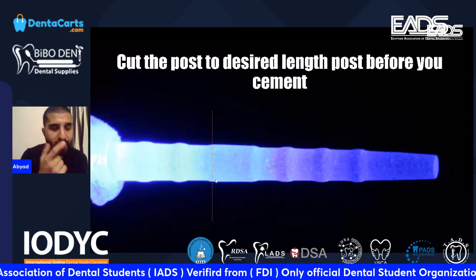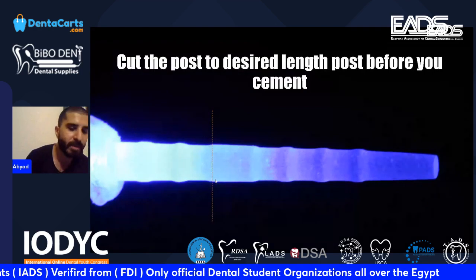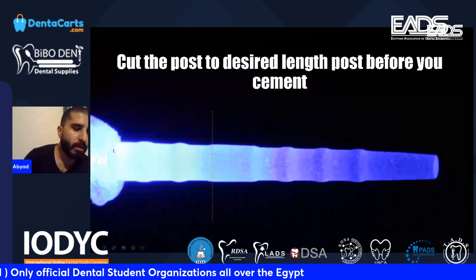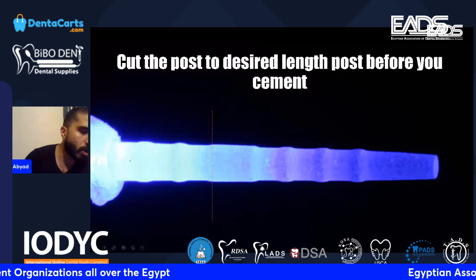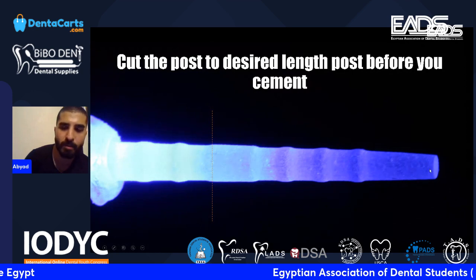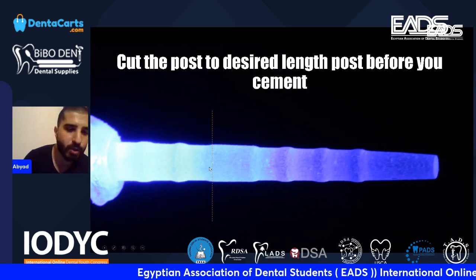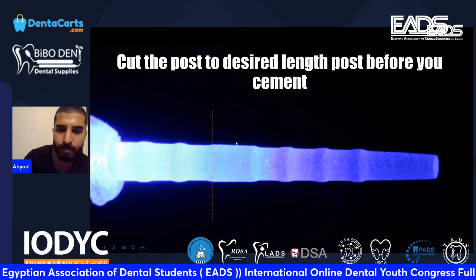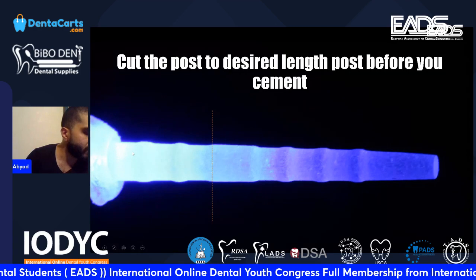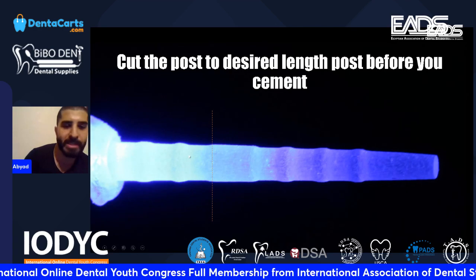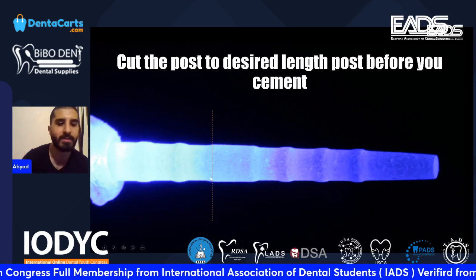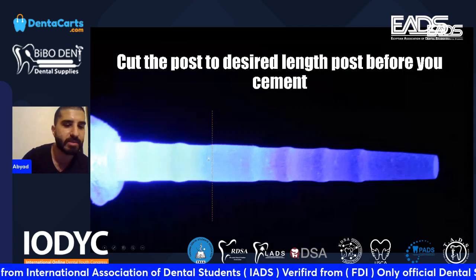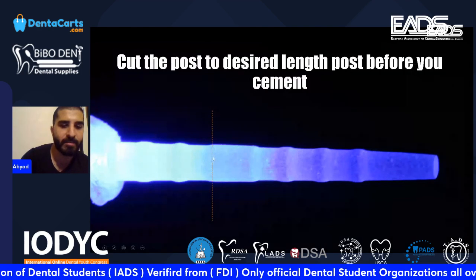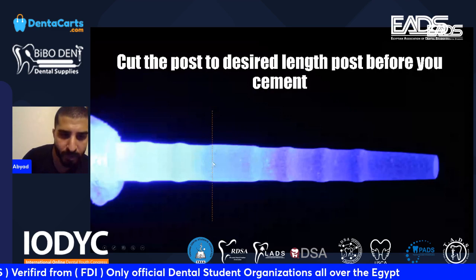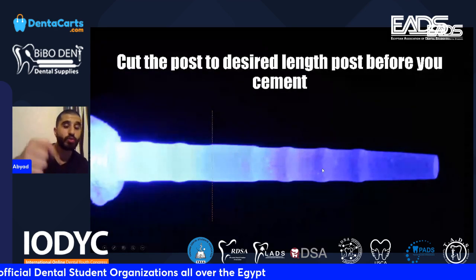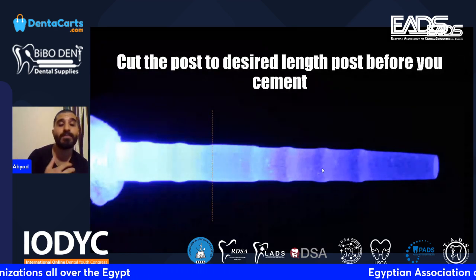The second thing is what I was saying right now. It's this trans-illuminating potential of your fiber post. Have a look. The irradiance and the power of your light is extremely strong here, but as you go in depth towards the end of the post space, it's getting weaker and weaker. So let's say you wanted to place a post which is this long. All of this is wasted light. Okay? All of this is wasted light. So if you cut it here before you cement, place your cement and then place it and get your light cure and start curing here, then you have gained the advantage of irradiating all of your post here within these 4 or 5 or 6 millimeters, which will give you initial bond strength which is acceptable.